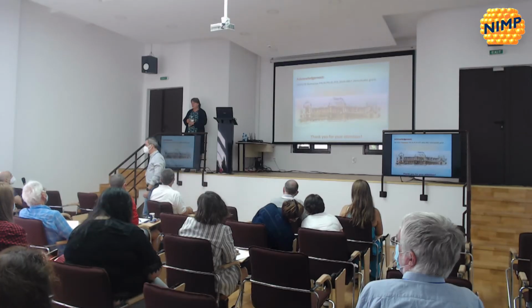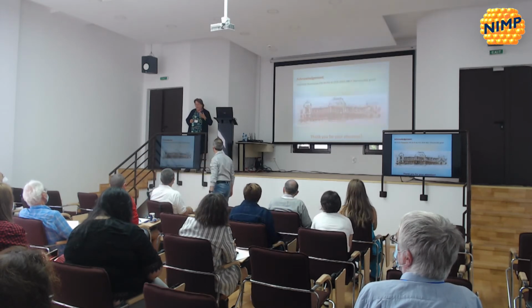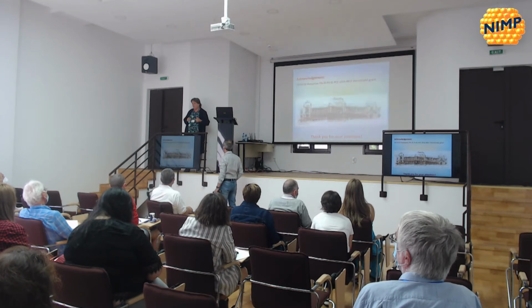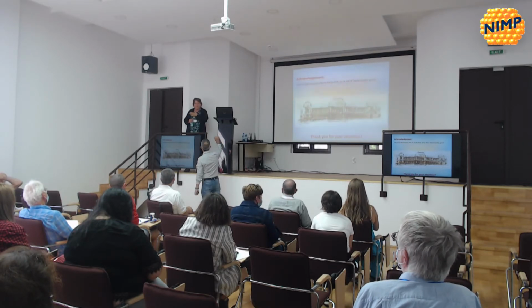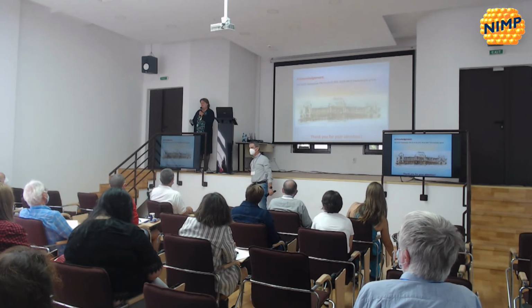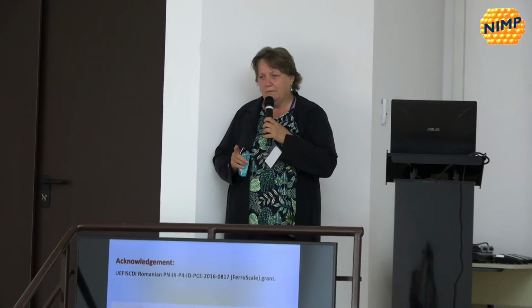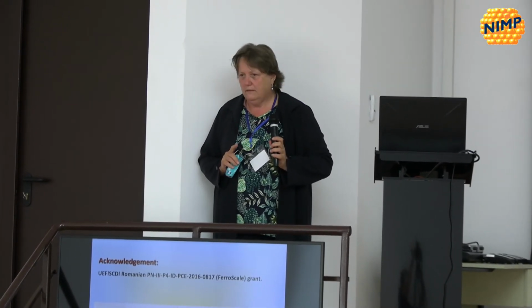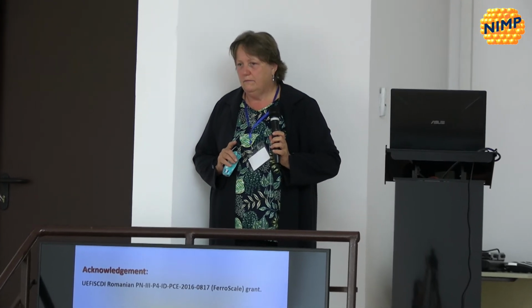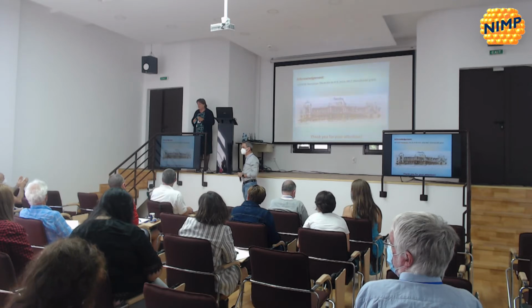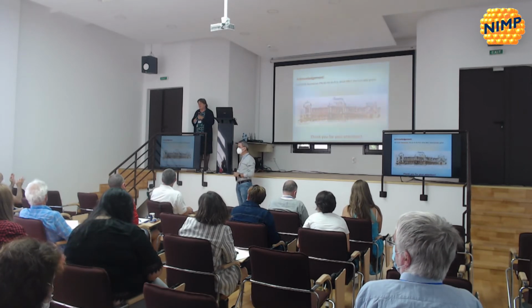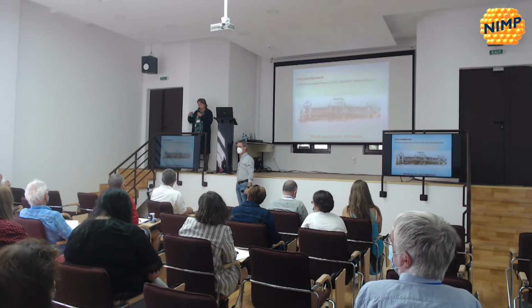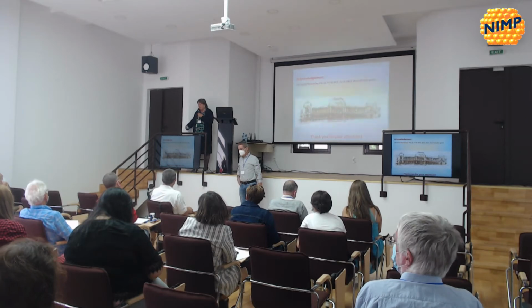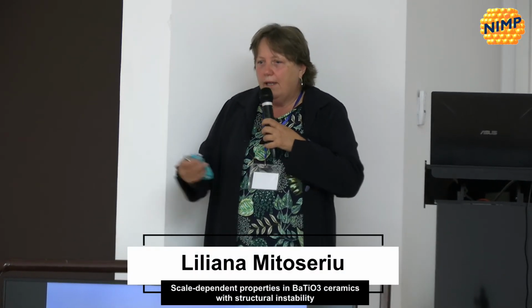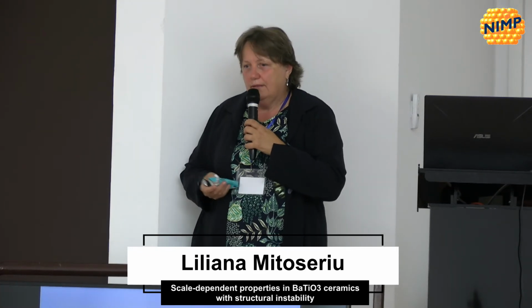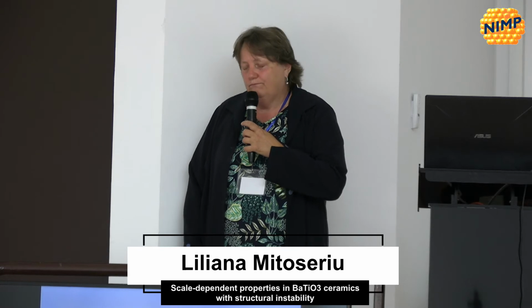It is a discrepancy indeed, because maybe one expected to have this extended phase superposition only at very small grain sizes, but maybe all of these dislocations that are all over the range of grain sizes maintain this even when the grain size is higher. I don't know if that is exactly what you mean. My question is for any given grain size. Yes, the dielectric constant as a function of temperature shows a relatively sharp peak. Yes, it is sharp. The X-rays as a function of temperature show a wide range of coexistence. Yes, this was strange also for us, because previously grain sizes in the same range, below 100 nanometers, looked very flat. So we wondered why the dielectric constant is still so sharp. Maybe the dislocation is the answer. I have no answer, really.